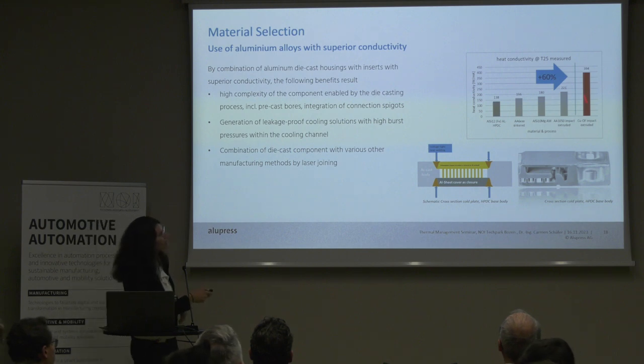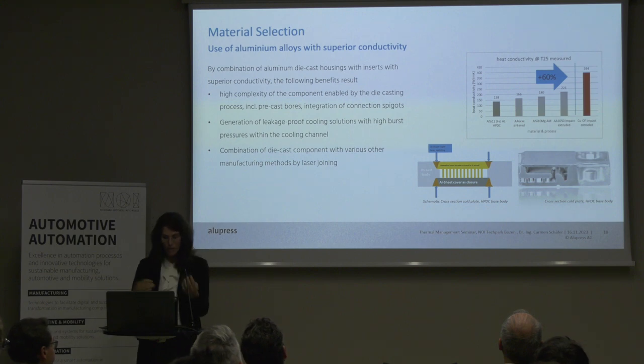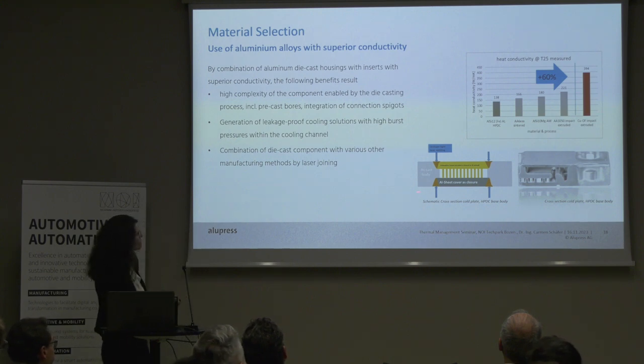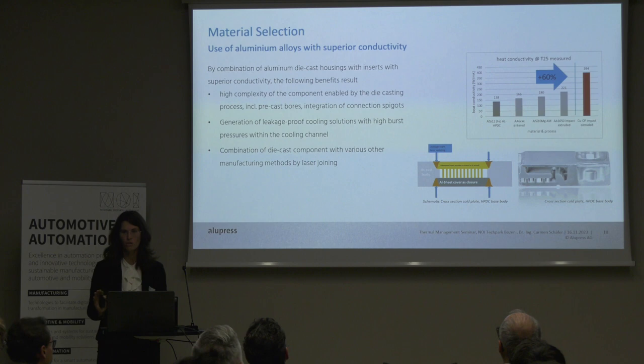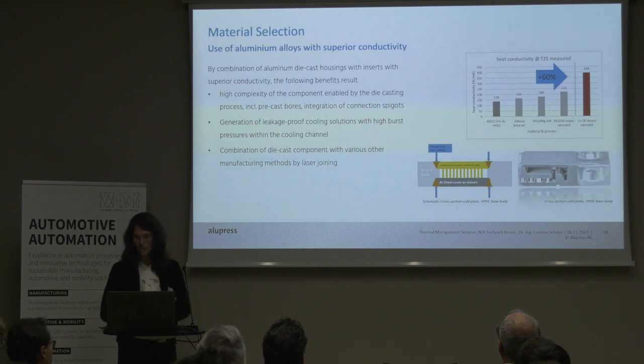If you don't need the copper, the 400 watt per meter Kelvin, that's where we start with the die cast. And there are some other options in between that I can use and combine with the die cast housing. So this is the cast body. You can put a sheet cover on one side to close the cooling channel, and you can put whatever pin fin structure you want on the other side. Wavy structure, pin fins, diamond shape, whatever you can get out of your CFD simulations.